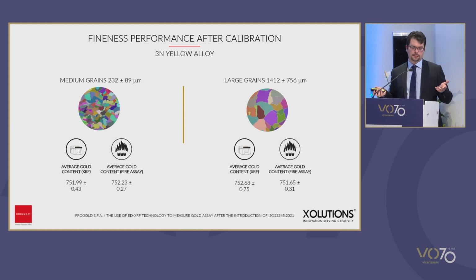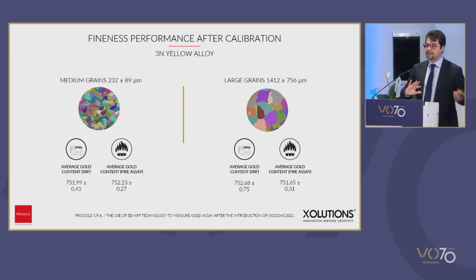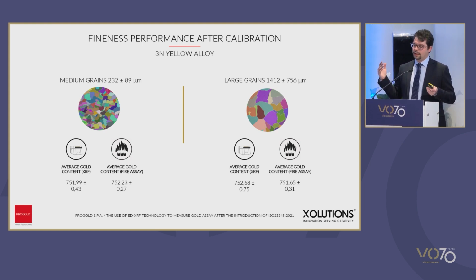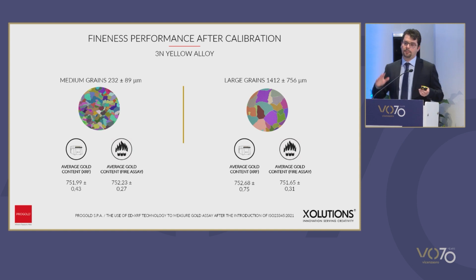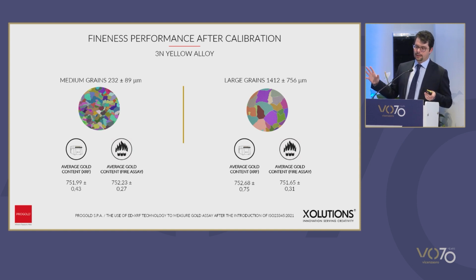And then we also did fire assay. So you see that there are slight differences in terms of fineness, both with fire assay and with X-rays, which are probably due to the fact that in order to obtain large grains structure, we used a different production method.